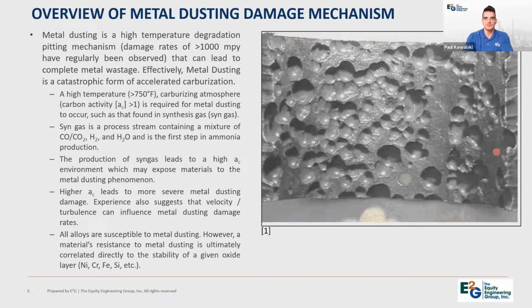So just a high-level overview of the metal dusting damage mechanism. Really, it's a high-temperature damage mechanism that can lead to catastrophic results or very severe degradation. We've seen damage rates as high as, well, over 1,000 mils per year. So obviously, this is very severe. It initially initiates as really localized pitting, as you can see here on this image, and then eventually results in just turning the metal to dust, hence the name.